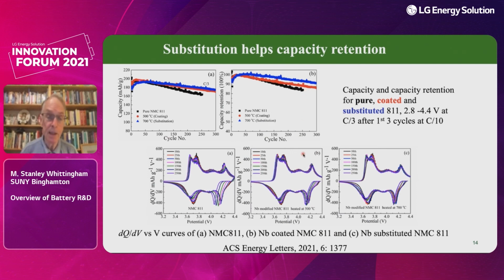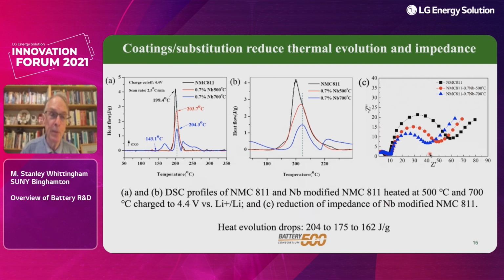Why is that the case? Well, we looked at these materials, and these are dQ/dV plots, and you see the unsubstituted, this voltage here shifts continuously. When we substitute it, there's very much less shift. So the material is much less reactive. We feel the surface is not changing as much, and therefore this material is being stabilized against reaction with the electrolyte and maybe against oxygen loss. So we did one more set of measurements.